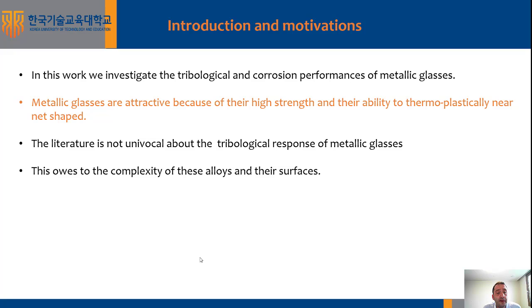However, the literature is not univocal about the tribological response of metallic glasses. One reason owes to the complexity of these alloys and their surfaces. So we need to keep in mind that metallic glasses are multi-component alloys with very often elements that are prone to build oxide layers, and for that reason the properties of the surface oxide may have a very large impact on the tribological performance of these alloys.